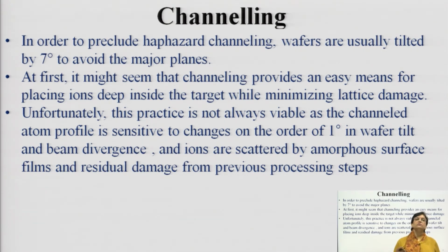To deal with this hazardous effect of channeling, what is the remedy? The wafer is generally tilted at 7 degrees to avoid major crystalline planes.